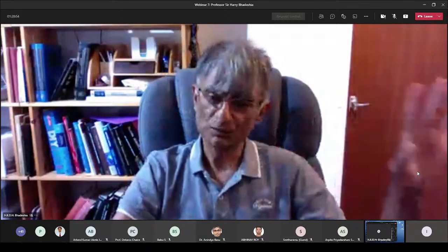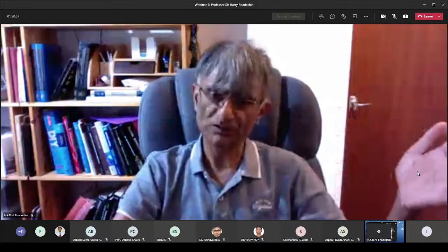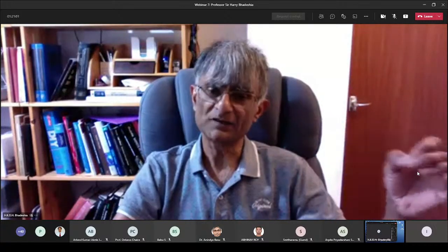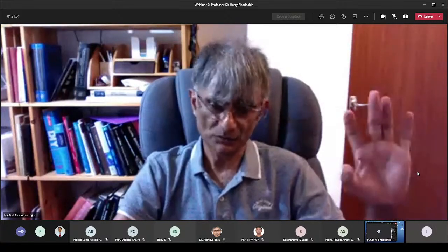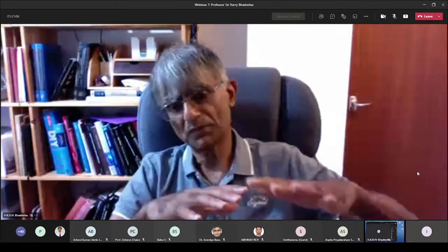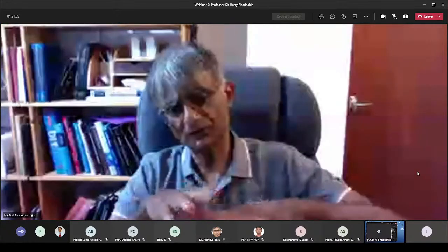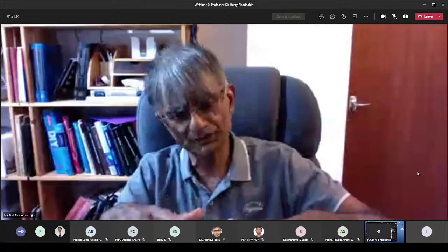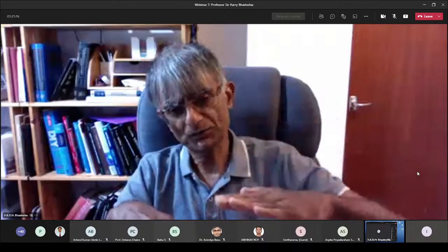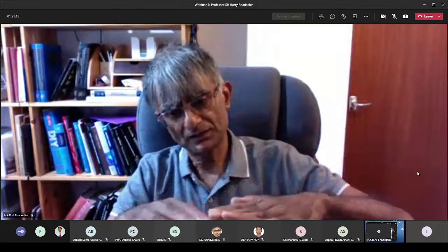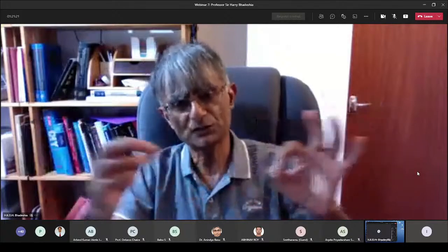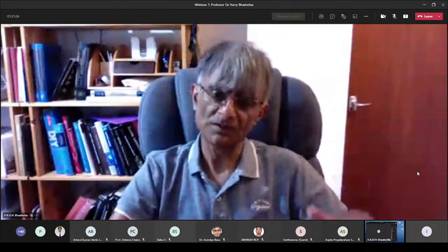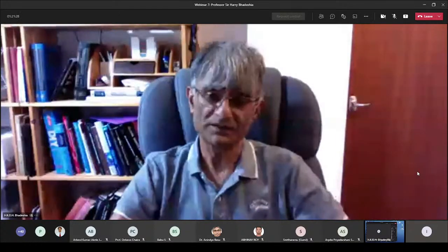But in low-carbon wrought alloys, the sort of steels you produce in hundreds of millions of tons, the acicular ferrite is basically bainite. It's no different from it. By the time you come to observe it, because of the low carbon concentration, many of the plates are touching and the morphology looks a little bit confused. But if you stopped the transformation at an early stage, you would see exactly those plates of bainite that I was showing you. So acicular ferrite in low carbon steels is the same as bainite.